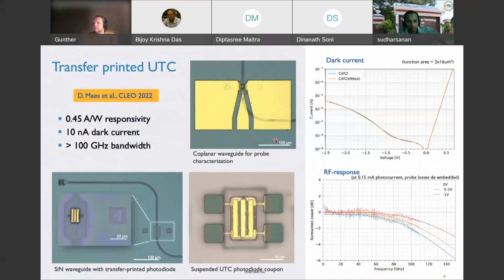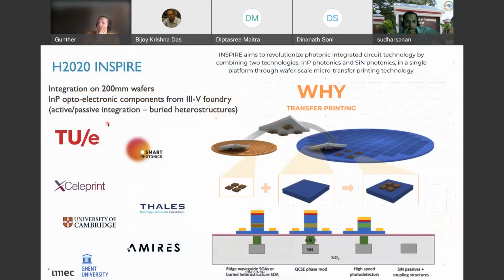Some very recent results that will be presented at CLEO later this year is the transfer printing of UTC photodiodes, so high-speed III-V photodiodes on silicon nitride waveguide circuits, where we get over 100 gigahertz of bandwidth and a reasonable responsivity in the C-band. So this kind of technology is now being developed further, as mentioned before already, in the context of a European project called INSPIRE, where the idea is to work with a III-V foundry to provide the C-band active devices, the SOAs, modulators, and detectors, and to transfer print these massively parallel on a 200 millimeter silicon nitride waveguide wafer.